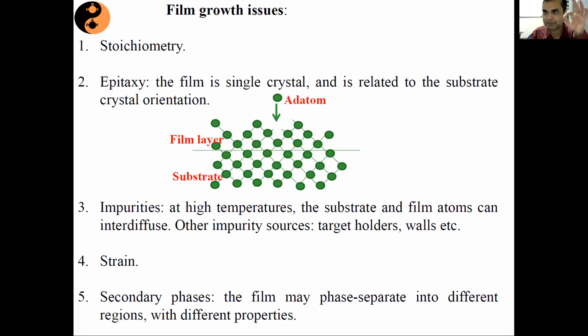That means those evaporants which are falling on your substrate, they just stay there and there only. So that means in that particular situation, since no diffusion is taking place, your films are mostly amorphous in nature or nanocrystalline in nature. That is why to get a good crystalline film, we should have sufficient substrate temperature, but not very, very high substrate temperature, because if your substrate temperature is very high, then substrate atoms itself will start evaporating and they will interact with your film and will create an impurity. Okay, so these are some of the issues that we will have to really understand.